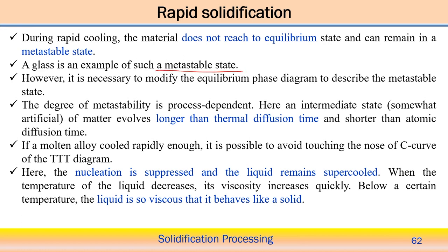However, to understand the metastable phase at a very high cooling rate, we need to modify the equilibrium phase diagram to accommodate the metastable states for this particular material. But the degree of metastability is process dependent, because the intermediate state is somewhat artificial. It involves a longer thermal diffusion time and a shorter atomic diffusion time as compared to the conventional process. So this molten alloy, when very rapidly cooled,